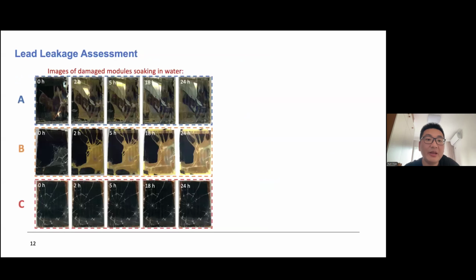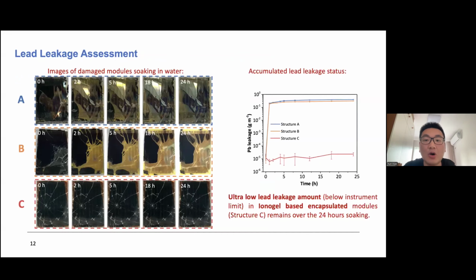So this is the image of the modules soaking in the water for 24 hours. From the lead concentration in the water, you can see that structures A and B are the typical encapsulant with a typical structure. The lead leakage is very quick, reaching saturation within hours actually. But our structure with ionogel remains with almost no net leakage for 24 hours of soaking. Actually, it's because this hail test does not break our solar module. So we're trying to do it against a more extreme condition.